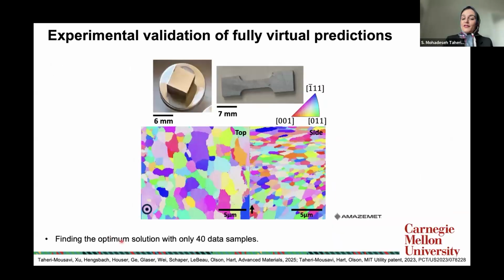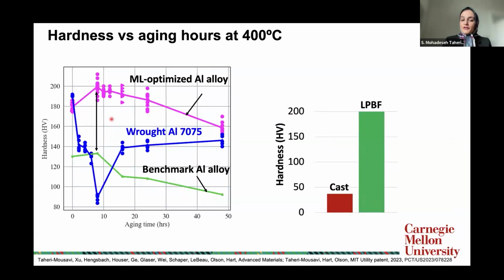In fact, with only 40 samples, as we show in this paper, which is now online, we found a new recipe for the alloy. We ordered a custom powder, we printed it, and we showed that our strength was 50% higher than that record alloy, and the same strength as wrought aluminum 7075, and it can also sustain its highest strength even at 400 degrees C for 48 hours. But the big news is also summarized in this figure. The same composition when cast had a strength 5 times lower. So it means that additive manufacturing has some tuning knobs that, if you use them, you can achieve unprecedented properties that you could not achieve with casting.